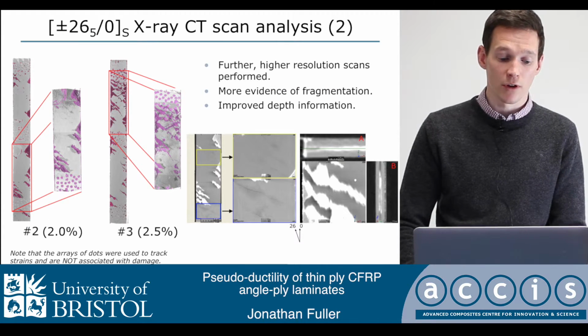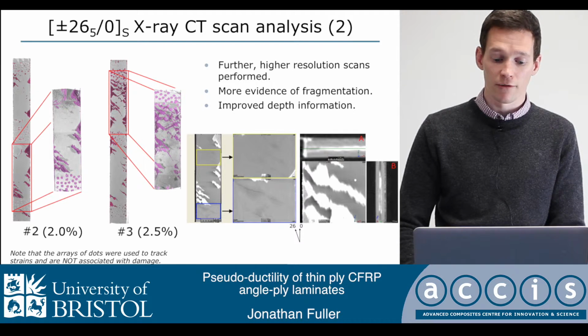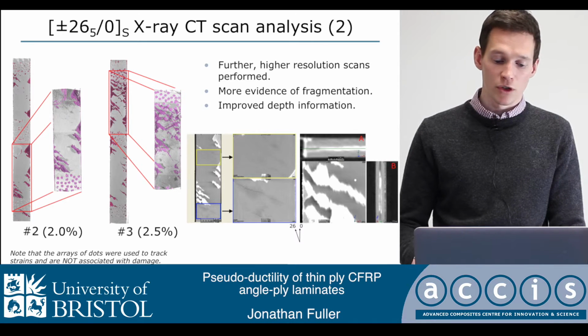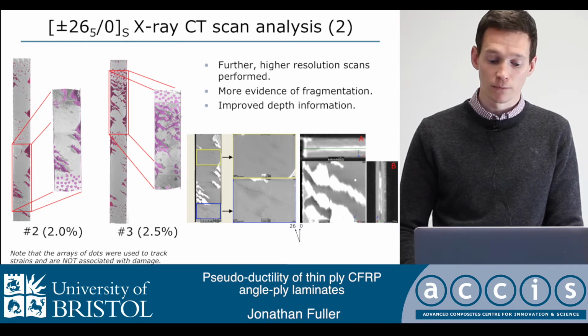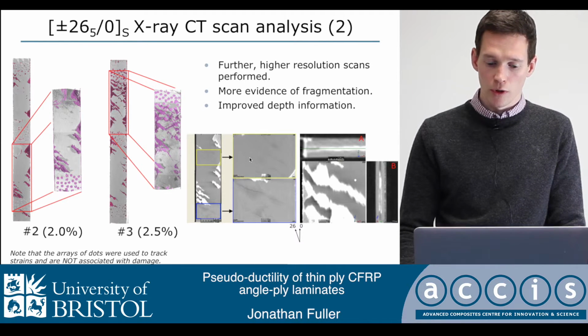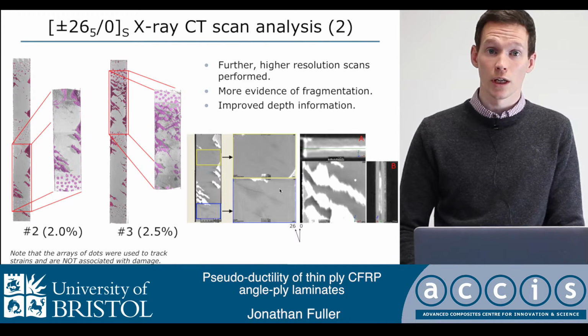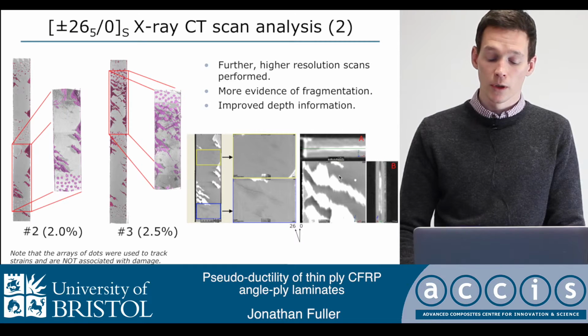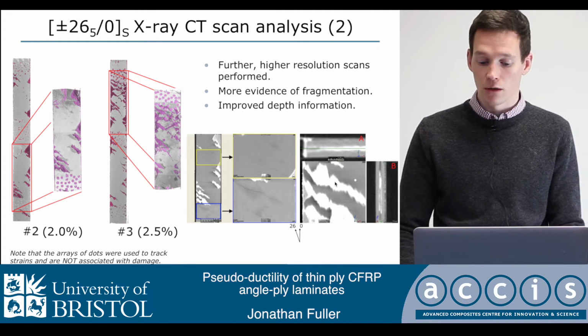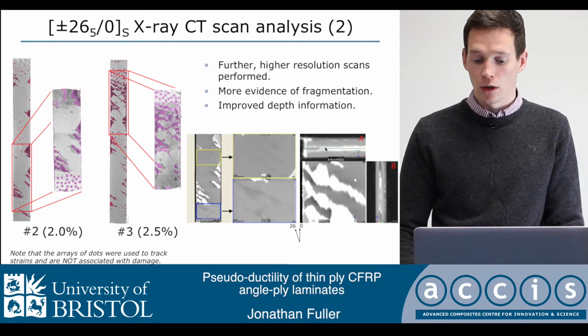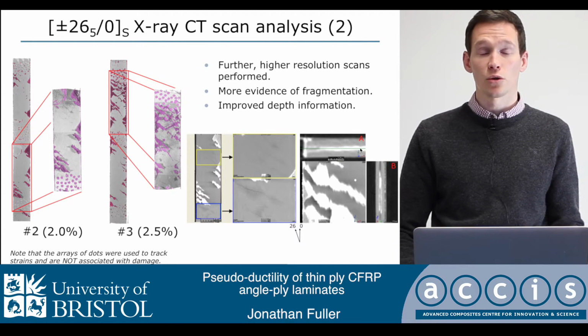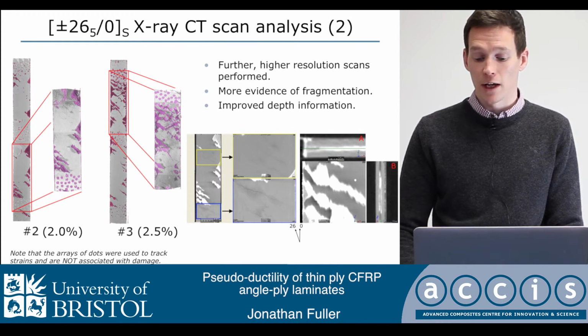And then zooming in on these specimens further, we were able to do a higher resolution scan on the two shown on the left. And this gives us a bit more evidence of fragmentation. So the yellow and blue insets on the central image show, hopefully you can see these lines indicated by the mouse, the fragmentations in the center of the specimen in the 0 degree layers. To the right of that, we can show that the specimen which has been loaded up further has actually developed these large white areas of delamination where the dye penetrant has got in. And also another key aspect of this image shows that the damage is solely residing in the midplane of the laminate, which backs up the initial work of the angle-plies suppressing damage all the way up to failure.